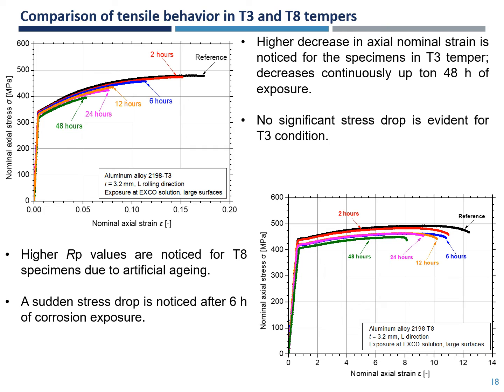Regarding the comparison of tensile behavior in T3 condition of aluminum alloy 2198, shown in the left figure, and the T8 condition, shown in the right figure, it was found that higher decrease in axial nominal strain are noticed for the specimens in T3 temper, while no significant stress drop is evident for the T3 condition. Higher yield stress values are noticed for the T8 specimens due to artificial aging, but a sudden stress drop is noticed after only 6 hours of corrosion exposure time.